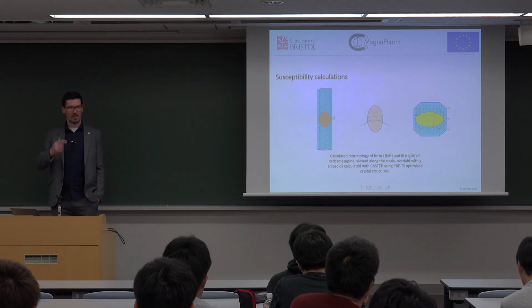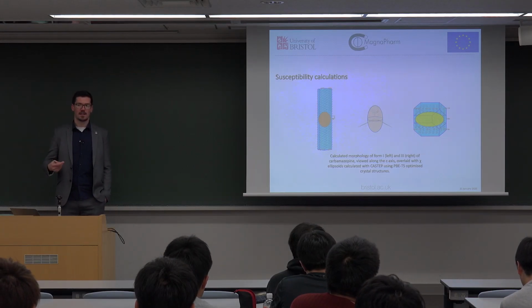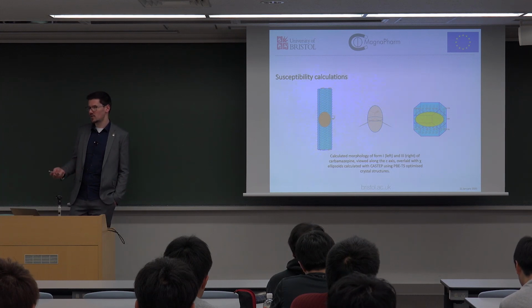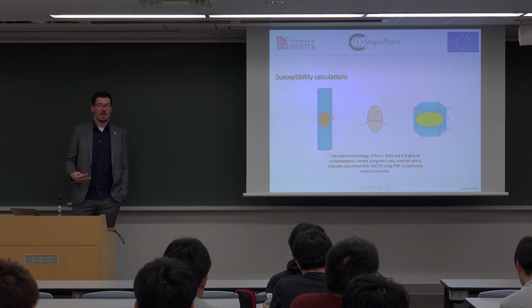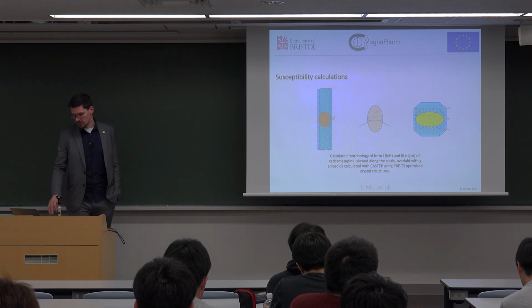Is that significant? Well, the susceptibility calculations would suggest that the form we get out of the magnet has a higher magnetic susceptibility than that grown in the magnet. I mean, make of that what you will. It looks like the magnetic anisotropy of the unit cell may not be an important factor when growing these crystals.